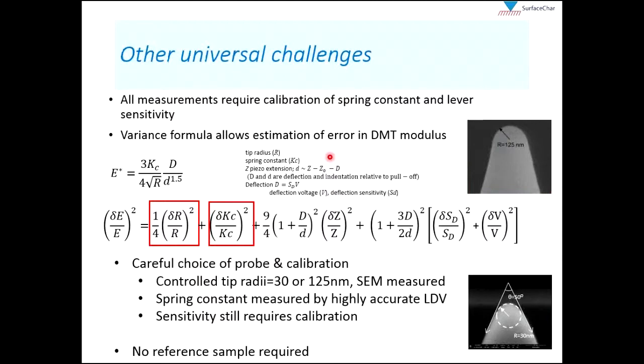So all the nanomechanical methods that I mentioned face universal challenges related to the fact that they're being measured with AFM. All these measurements require calibration of our spring constant and lever sensitivity. And so we can look at the formula for the modulus by the DMT model. The DMT model is basically the Hertz model with adhesion, and we use a variance formula to estimate the error of different variables to this formula. And we can see that tip radius and cantilever spring constant are significant and do show up in this equation, and are errors that we need to worry about.